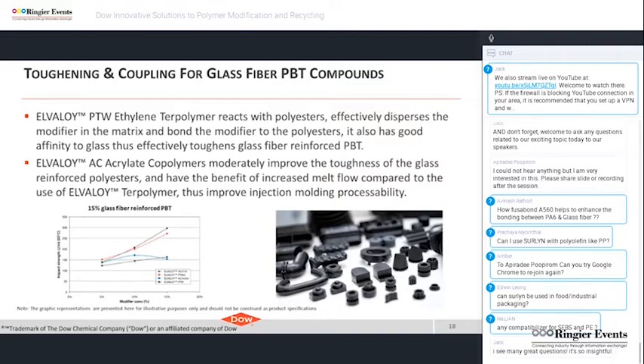The chart shows the impact strength of 15% glass fiber reinforced PBT with 4 of our modifiers at 5 to 15% level. The Elvaloy PTW shows the highest impact in this comparison. Elvaloy PTW increases melt viscosity, which is not good for injection molding process. Hence, we cannot add high amount of Elvaloy PTW. Typically, 3 to 5% Elvaloy PTW is enough since glass fiber system does not need high toughness.